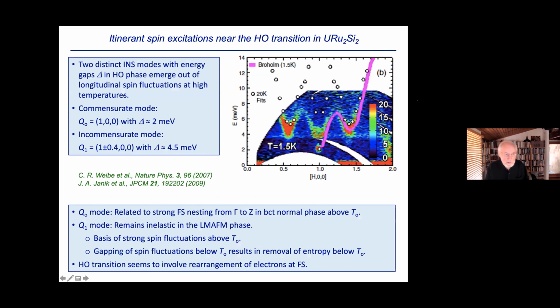Okay, so this is just quickly the inelastic neutron scattering measurements. So remember, there's a commensurate mode with a gap of about 2 meV. It's located right here. So you see, here's the gap. And then the incommensurate mode at this wave vector with a gap of 4.5 meV. And you see it here and here in these neutron scattering spectra. So the Q0 mode is related to strong Fermi surface nesting from gamma to Z in the BCT normal phase above the hidden order transition. So it's kind of related to the ordering. It goes away when you go into the ordered state.